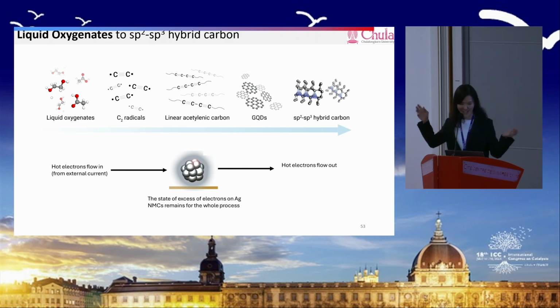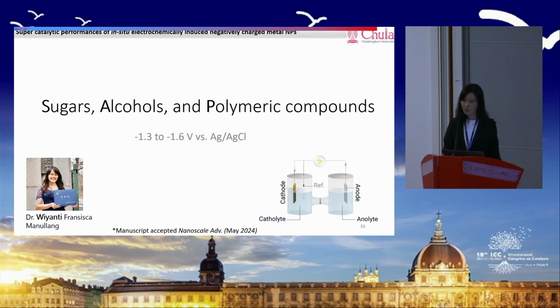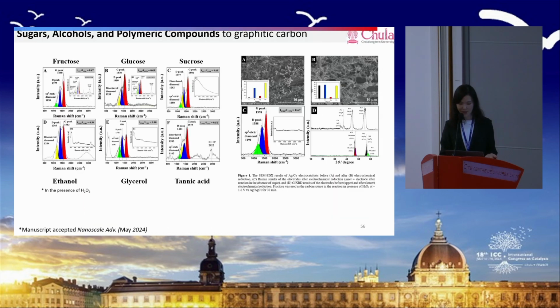Okay, and this is just our proposed idea, from the liquid oxygenates reduced into C2 radicals, to grow linear acetylenic carbon chains from graphene quantum dots, and on silver in particular, that can induce sp2, sp3 hybrid carbon formation. And yes, it works with biomass-derived compounds. Usually, if you want to convert these biomass-derived compounds into graphitic carbon, you need maybe 1,000 or 2,000 degrees to make it graphitic. But here we convert these sugars into graphitic carbon at room temperature.